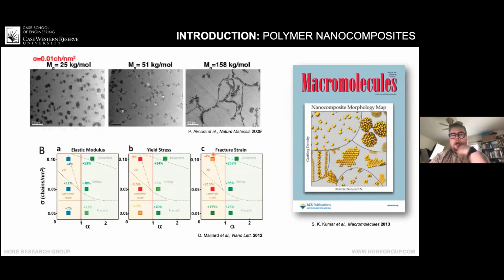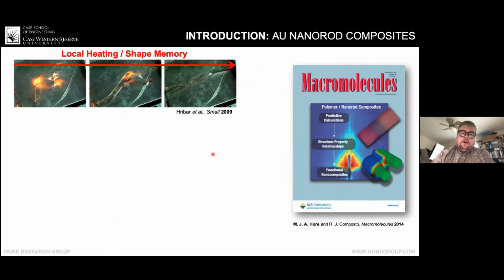So we can move beyond spherical particles and look at other things that are maybe more responsive, such as gold nanoparticles. I'm showing you an example here where this is a polymer, not really a film, but a thin strip of polymer that has a small amount of gold nanoparticles in it, and it's initially created in this kind of spiral shape here.